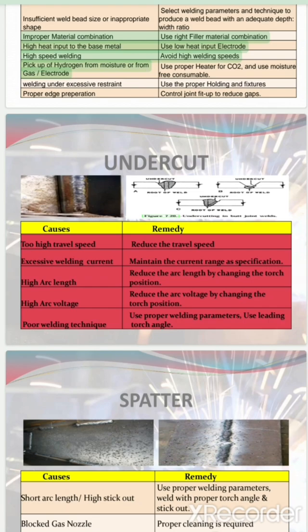Pickup of hydrogen from moisture or from gas / electrode. Use a proper heater for CO2 and use moisture-free consumables. Welding under excessive restraint, use proper holding and fixtures. Proper edge preparation, control joint fit up to reduce gaps.